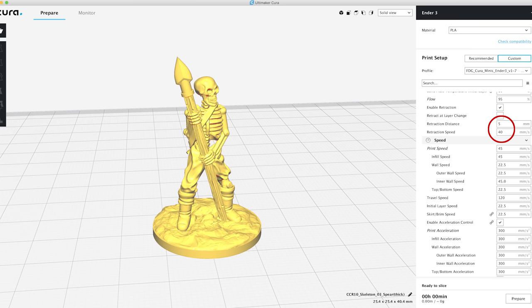I've done speeds up to 55 on my Ender 3. I did not notice any appreciable increase in retraction effectiveness, so I backed it back down to 40 simply because the slightly slower speed does not dig into that filament as much and you don't risk that under extrusion. So again, I'm going to touch on retraction in a lot more depth in another video, but just not this one.